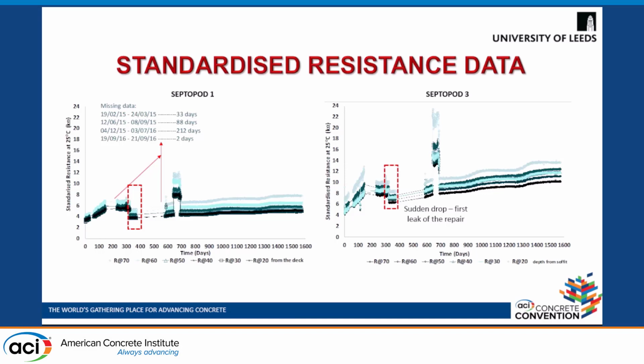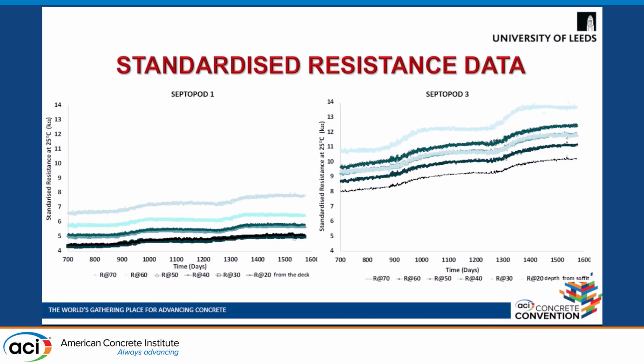However, there was another increase in the resistance, which was around 600 to 700 days. This was because there was a change in the frequency of data being captured. And secondly, the nearby areas of the bridge were heated up to get rid of the moisture inside, so that led to an increase in the resistance. However, after 700 days, there was a continuous increase in the resistance. So for further analysis, we are using the data after 700 days.